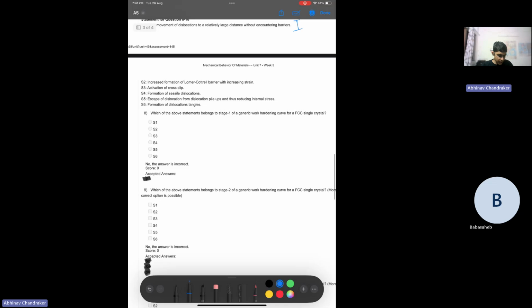Easy glide due to very few mobile dislocations and less obstacles. In second, increased formation of Lomer-Cottrell barriers with increasing strain. So locks have started to form due to cross slipping and dislocation. Some portions of dislocations getting stuck while cross slipping. So this will be stage 2, activation of cross slip.